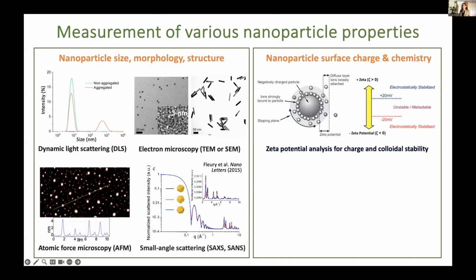Moving forward with surface charge and chemistry. For determining surface charge, zeta potential measurements have been very common, which can tell you obviously the surface charge, but also the colloidal stability of the nanoparticle. So it's typically assumed that highly charged particles, either positive or negative, will be electrostatically stable versus the more neutral ones between plus 20 and minus 20 millivolts will be more unstable, which is good to know before we put them into the plant samples.